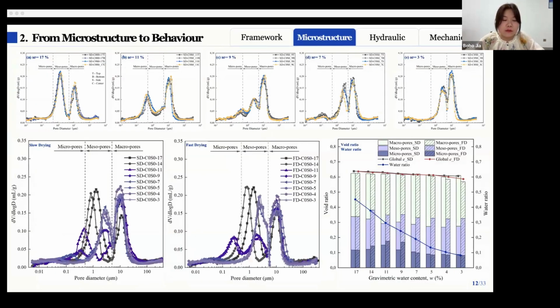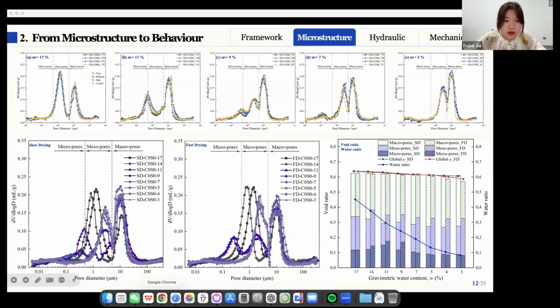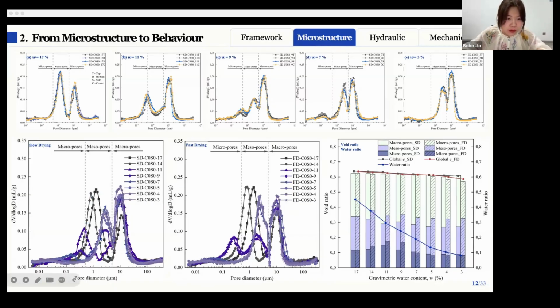And from this point, we can move to the microstructure analysis. Here we show the pore size distributions and the pore fractions at different water contents for the C0 S0 sample under slow drying. We can first see that at each water content, the PSD curves from different parts of the sample almost overlap, indicating that the pore structure is very similar throughout the sample. This is because under slow drying, the sample dries in a relatively uniform manner. And when all PSD curves during drying are plotted in the same figure, it can be observed that the pore size distribution evolves from bimodal to trimodal, and then back to bimodal.